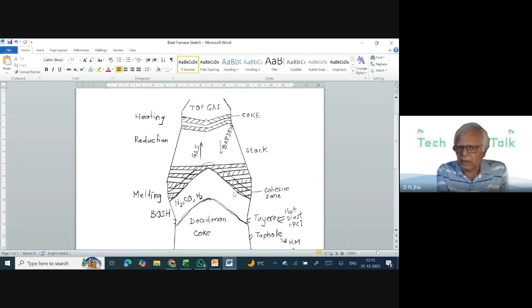Now, for the time being, let's understand that this is the melting line. Below that, we have got the deadman coke. And this is, like you can see, the hashed portion. As it comes down, there would be some amount of coke which will get released, because to maintain the shape, there is no support from the metallic burden. The metallic burden is supporting the thing which is above this. So if this is getting molten, then the coke also falls from here.